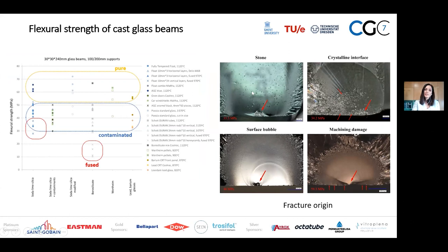The more pure glasses that we have tested over here had the higher strength, between 50 and 70 megapascal, and they failed mainly due to a machining damage. The more contaminated series, on the other hand, had a bit of a lower strength, between 30 and 50 megapascal, and they failed mainly due to a stone occlusion or a bubble in their surface. And finally, the samples that we have done at a lower temperature, so the fused ones, failed at low values, even 10 megapascal, and that was mainly due to their fused crystalline interlayer.